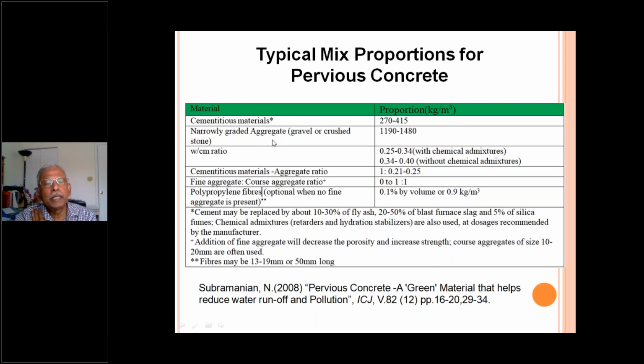And narrowly graded aggregates are used. That is the 1190 to 1480 kg per meter cube. Water cement ratio is 0.25 to 0.34 with chemical admixtures, and 0.34 to 0.4 without chemical admixtures. As I told you, 0.3 is the normal thing adopted. Cementitious materials versus aggregate ratio is 1:0.21 to 0.25.